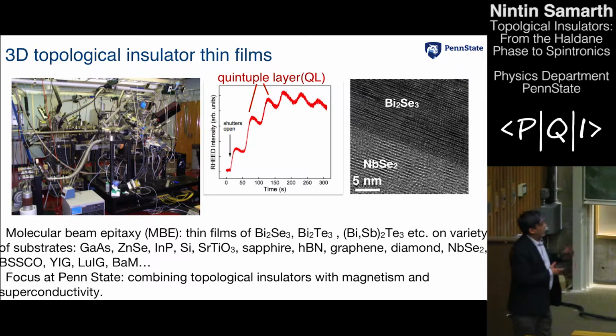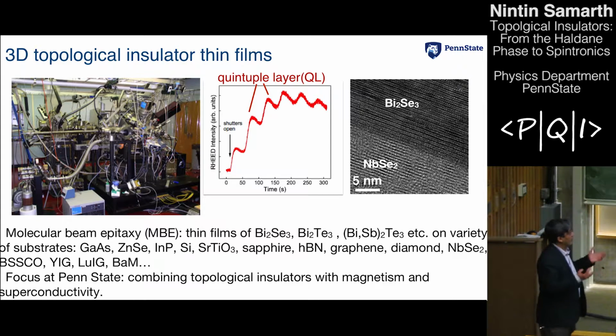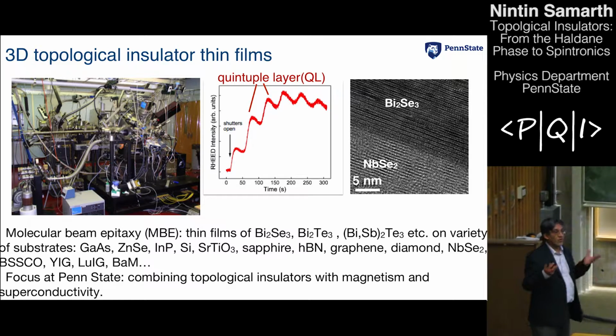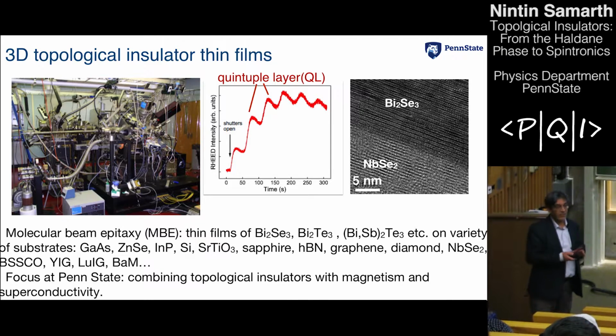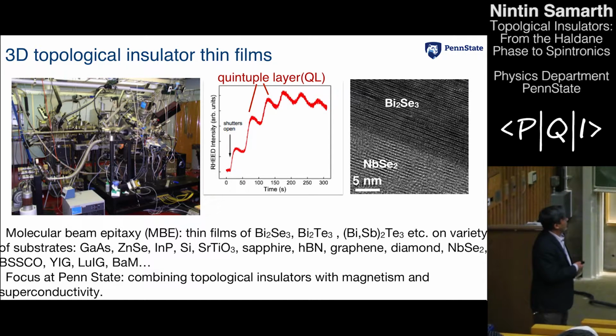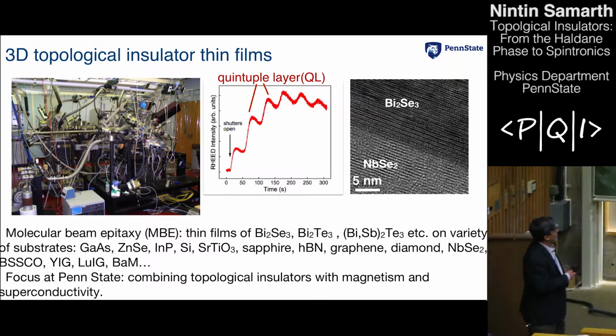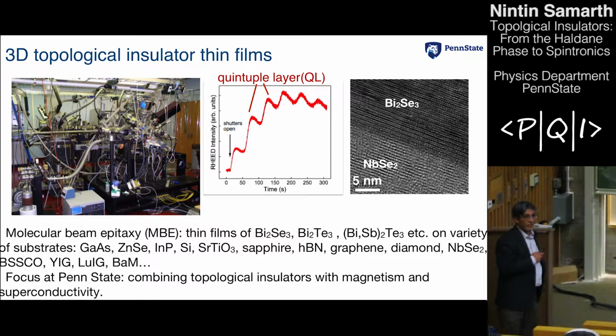Now, I got interested in this field roughly at this point where these bulk crystals were being grown and people had started making to some extent thin films in labs in China, and we got interested in using our method of synthesis to grow crystals of these systems, so make thin films of these systems. So the way we do it, and I'm not going to go into too much detail, is by using ultra-high vacuum chambers. So this is the lab in which it's done.